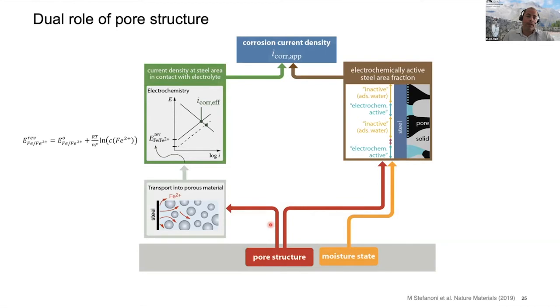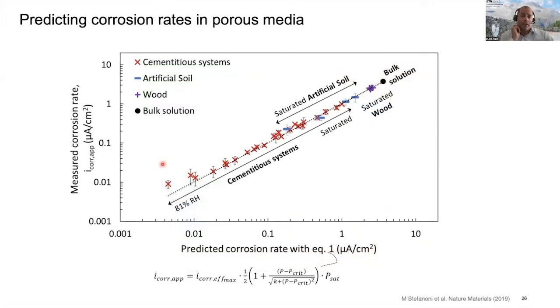In addition to that, there is also an electrochemical effect because the pore structure influences the extent to which the ferrous ions in the electrolyte can move away, and that controls the concentration of Fe2+ at the steel surface, which then also has an electrochemical effect on the corrosion kinetics. By utilizing this concept, it is possible to predict corrosion rates of steel in carbonated concrete very reliably, as you can see here, and actually also to predict corrosion rates of steel in other porous media, such as soil or wood.